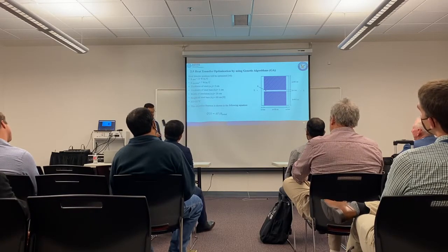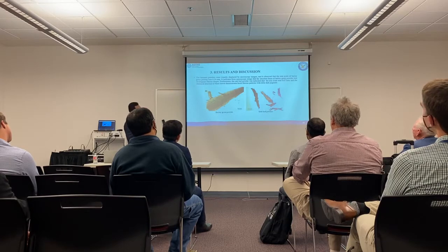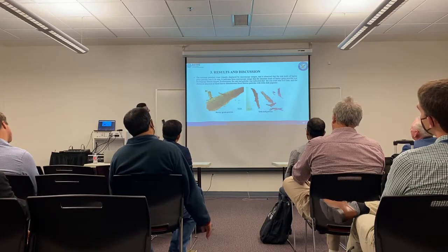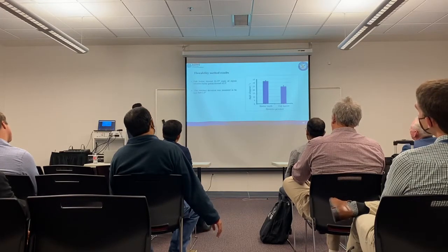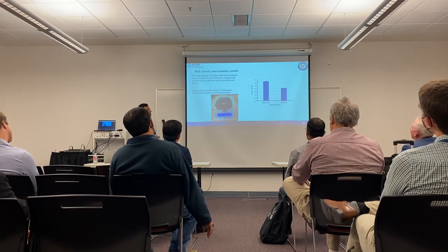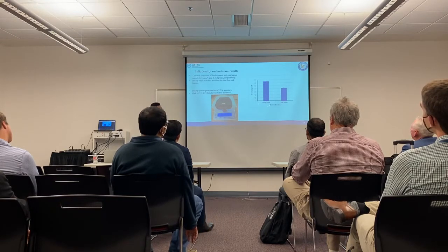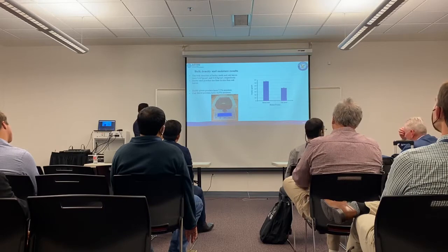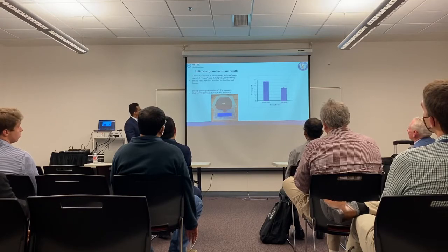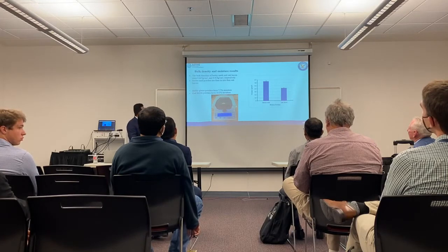optimization for our problem. Our results, this is for biomass materials. These two are for powders. This is the scale size of each one, sorry. For the density and moisture results, we have, for example, here, barley seeds and oak leaves. We ran it five times, and we have the standard deviation for that. After that, we could see that barley seeds are finer in size than oak leaf, and we have 7.7% moisture for barley and 10.5% moisture for the oak leaf.